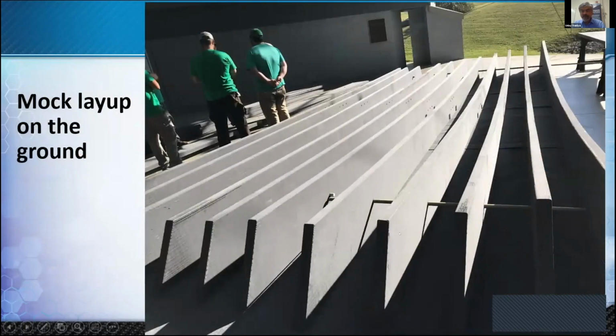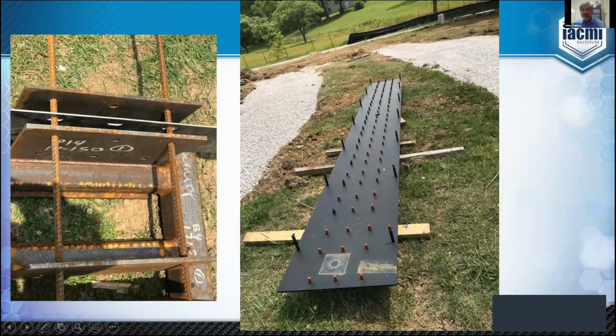Finally the beams were finished and brought onto the site. They were placed upside down first to check for alignment, because this rod would connect all of them and pass through them, and this is the same on the other side. So this check had to be done on the ground. And this was the fixture which would hold them to the superstructure. You can see this width here, where each of the beams would pass, and those holes that I showed you in the beginning are where these rods would pass through. That's how the beam gets supported to the superstructure.